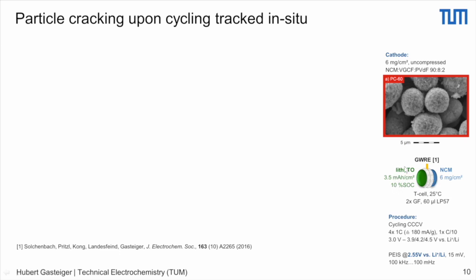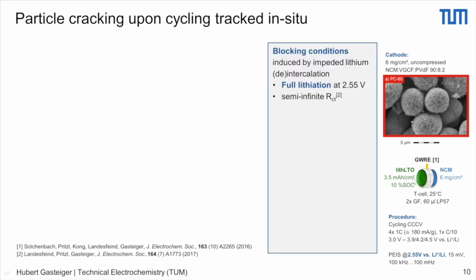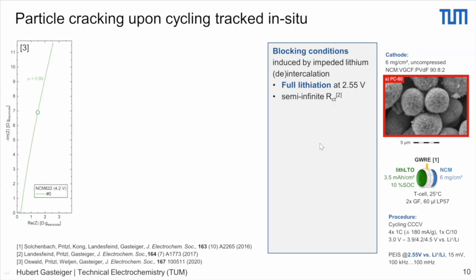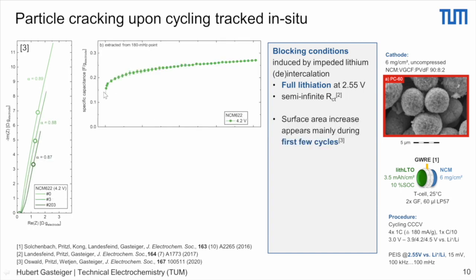And we utilize a pre-lithiated LTO electrode because that allows us to bring the cathode electrode after each cycle into blocking conditions, meaning completely charging the electrode, where we know that the charge transfer resistance becomes very large. So we get the almost semi-infinite charge transfer resistance. And this allows us to get, again, a blocking condition signal from which it is very easy to quantify the capacitance. So this is shown here for the first cycle. So if we then cycle the material, of course, the number of cycles comes a little bit later. These are, I believe, 200 cycles.